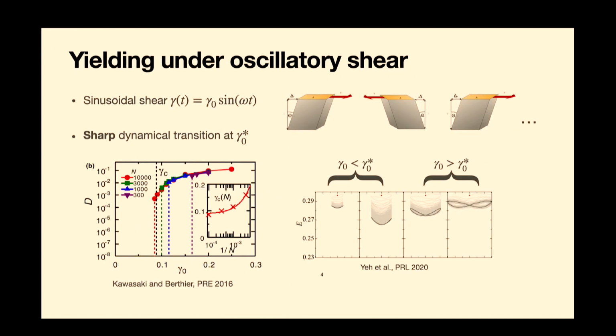Okay, so here it is. So essentially we have a shear strain which we'll call gamma. We oscillate that in a periodic fashion with some angular frequency omega, and basically you do this to your system, you go backwards and forwards. Okay? And so what's been known for a few years from simulations, for example, from Ludovic Berthier's group, is that these systems are actually interesting because as you vary the amplitude of your perturbation, right, you get a so-called dynamical transition.